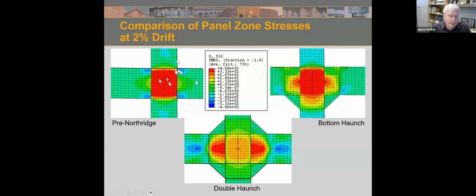And that was the configuration that was in that situation in the existing building. When we put the bottom haunch on the right here, that didn't really take away that yielding in the flange and in the panel zone. So we still had that kinking going on, and this is where that fracture occurred in that top flange. So pretty interesting result. Once we went to the double haunch, you can see the panel zone gets very quiet, not much yielding going on. You're getting a little yielding in the web of the member, but that wasn't anywhere near any of the welds that would fracture. And so, kind of validated that the double haunch was a really good approach.